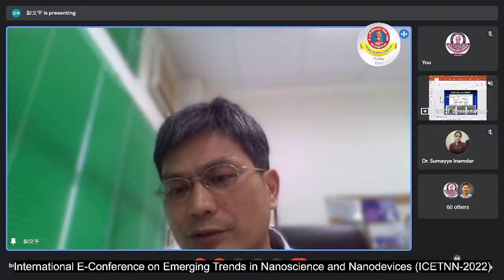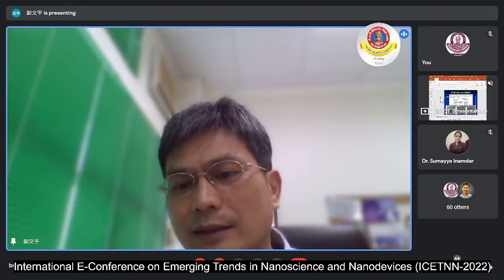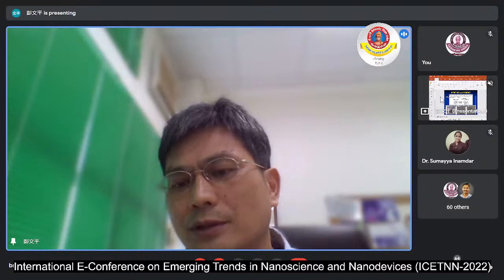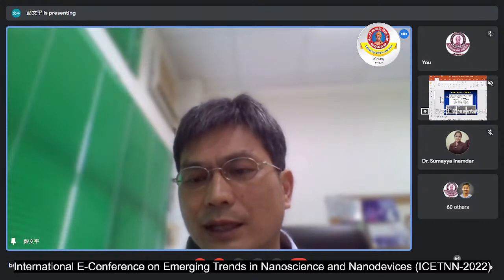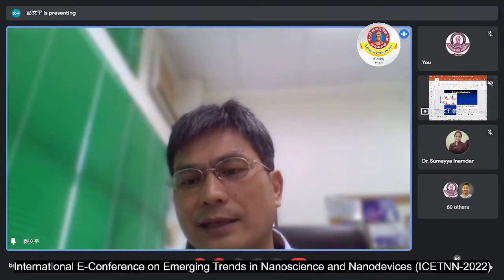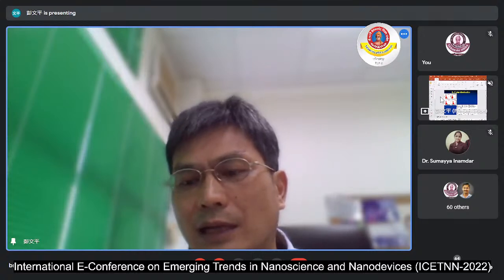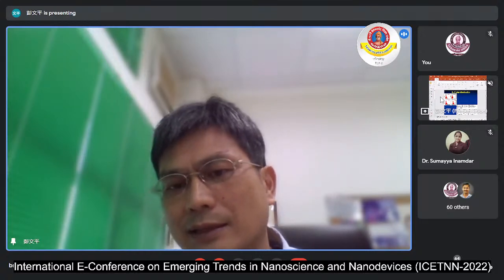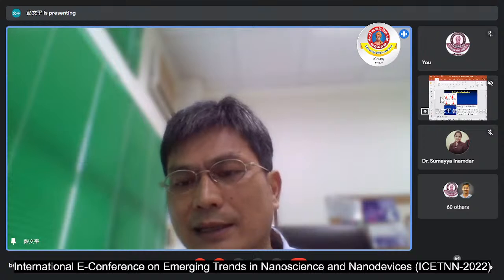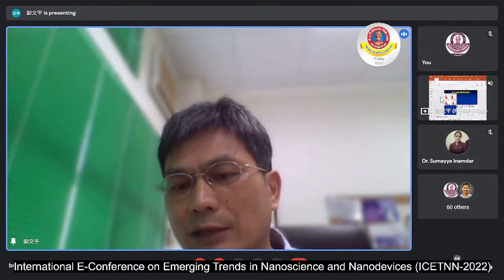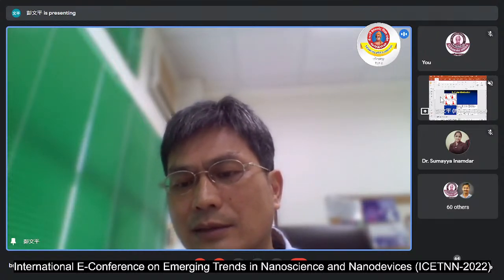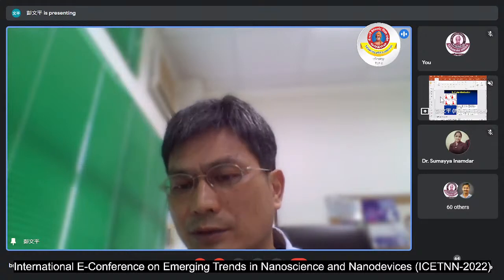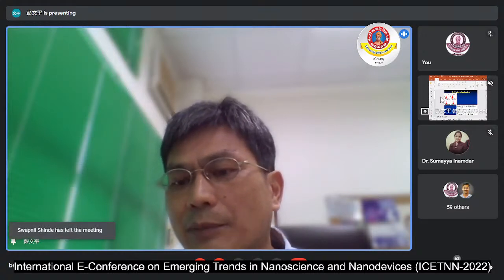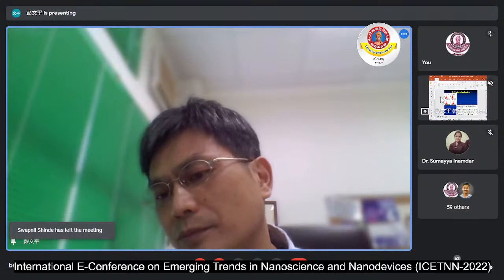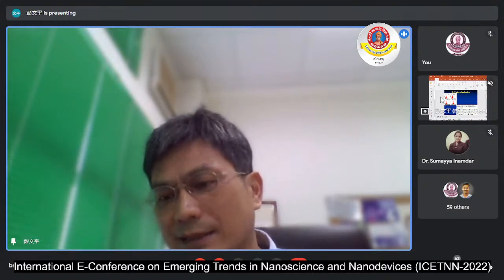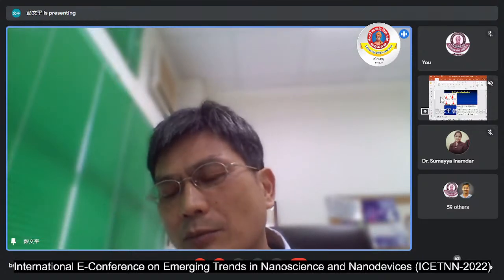The TEM shows the size of this and the high temperature, high pressure diamond are closely related, on the same scale. Using dynamic light scattering, the particle sizes we measure for both the HPHT and the oxidized nanodiamond are very close. Also the zeta potential is minus 52 millivolts, so they are at the same level, almost the same level.